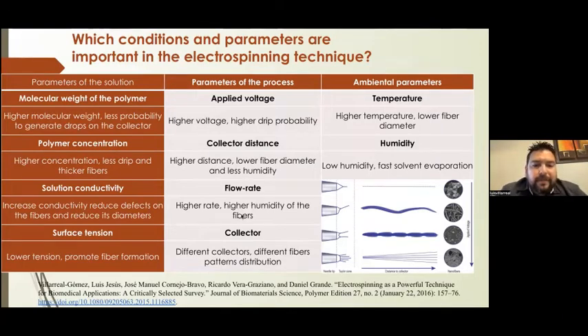Parameters. Electrospinning fibers is not that easy. It's easy, but you need to take into account different parameters to create beautiful nanofibers, well-defined fibers with reproducible properties. You can take into account the molecular weight and concentration of the polymer. You can select the correct solvent to give conductivity to the solution, and you can work on the surface tension of the final solution.